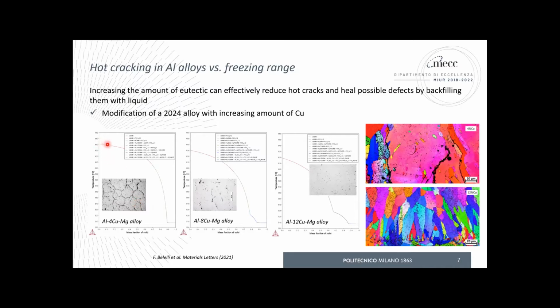Of course, here we also have some information about the solidification curve, which was calculated based on its own composition by Thermo-Calc, assuming Scheil-Gulliver solidification conditions. So no diffusion in the solid phases and ideal diffusion in the liquid with equilibrium at the interface, right? And we got this kind of curve, which shows a sharp drop in the temperature in the last stage of solidification. If we add more copper in the alloy, the curve is modified and the amount of cracks is reduced. And if we add even more copper in the composition, we drastically modify the solidification behavior and we can remove all the cracks.